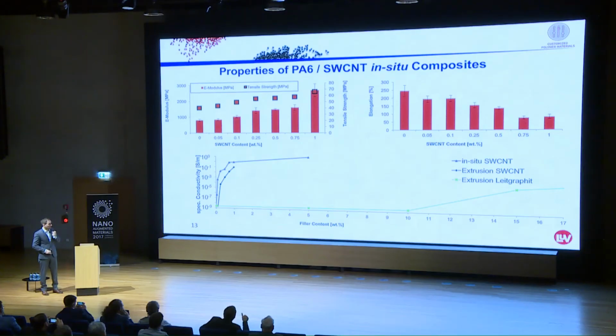And for those of you who are not familiar with compounds at all, let me show you how much of a macroscopic filler you need to reach anti-static behavior with an extruder, such as conductive graphite here. We are talking about 15 to 20% to just reach anti-static. So even if you use an extruder with the TUBALLs, it has really a high performance, I have to say.